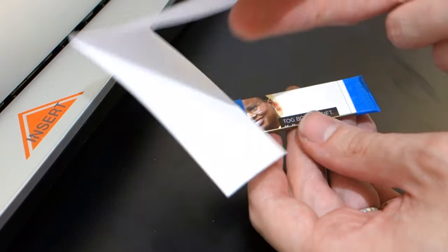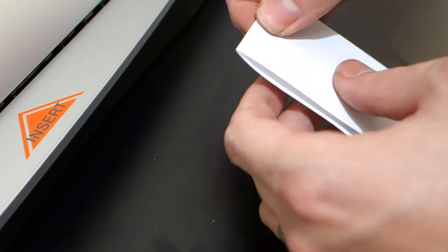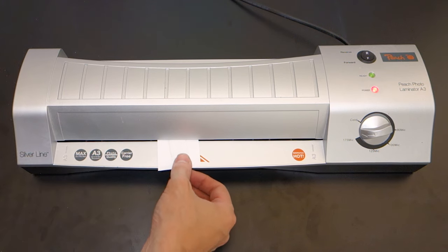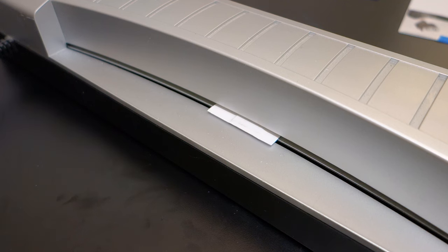However, if you care about your laminator, it is a good idea to make a small paper sleeve for your plaque so you don't mess up the laminator. Make sure the laminator is set as hot as it will go, and continue to feed the plaque through the laminator 5-10 times to ensure enough heat is transferred into the brass and that the toner will stick down properly.